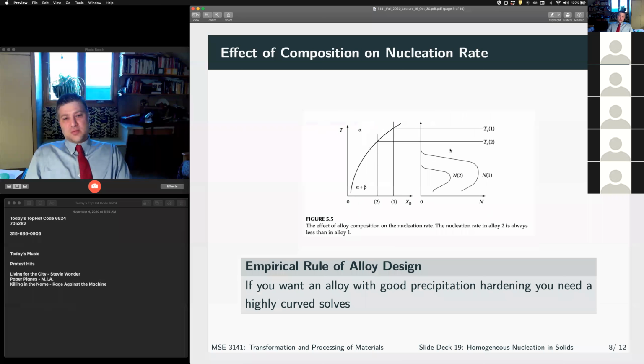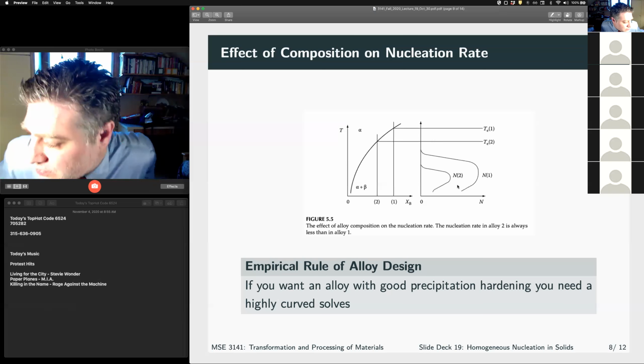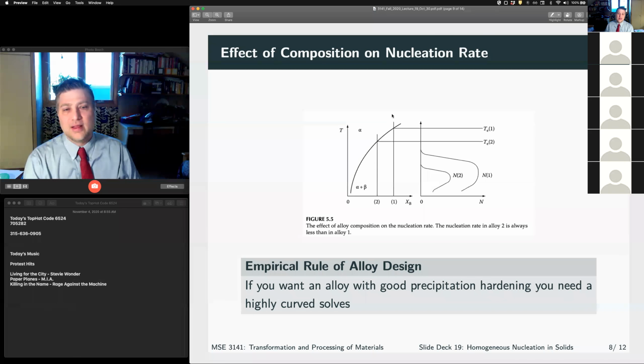I want to point something out here, that the nucleation rate is going to be dependent on the composition, right? Both in terms of the mobility and in the undercooling, right? If I'm at composition 1, for any given temperature, I have a larger undercooling, but my diffusivity is essentially the same, right? So that means that the richer I am in supersaturation, when I come down into the two-phase region, the faster my nucleation is going to be. Right? Does that make sense? It follows our intuition, right?